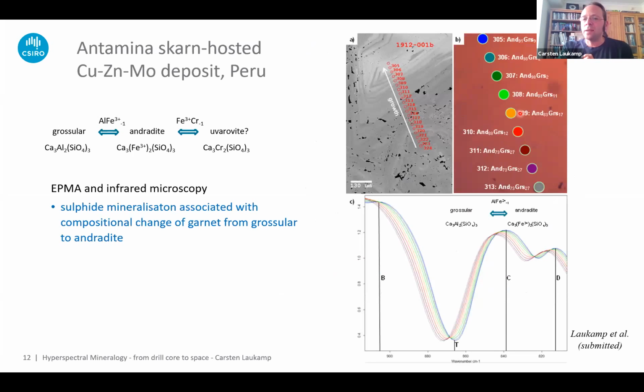But when we look at the garnet composition, then it gets more interesting. And we had a closer look. We did some microprobe analysis and infrared microscopy as well on different garnets. And we basically found various grossulars and andradite, and we went to the very detail here. This is just a backscatter image of this zoned garnet, and the corresponding infrared reflectance spectra, and we see these absorption features here in different colors, according to the plot on the top right. And we see that these absorption features shift.